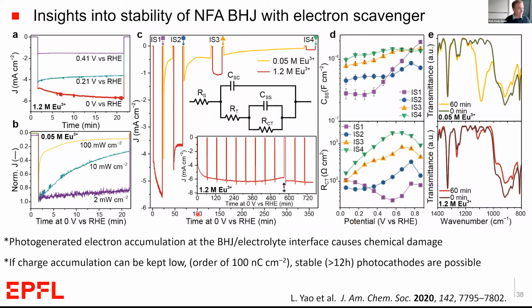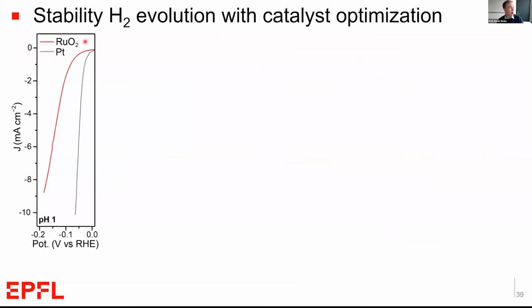In fact, we can quantify how much charge we need to keep low on the surface to give stable operation. So what that suggests is that we need to coat the semiconductor with a really good hydrogen evolving catalyst to extract the charges very quickly in order to achieve stable performance for a long time. And so we tried many different catalysts, and we found one, this ruthenium oxide.